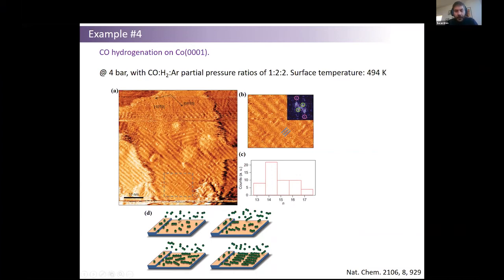But as the reaction proceeds, these linear hydrocarbons start occupying also the terrace sites. And because the terrace sites are occupied after a certain point, as is captured in this image, there is no active site available for methane formation anymore. That's why the selectivity of the cobalt catalyst changes after 2 minutes.